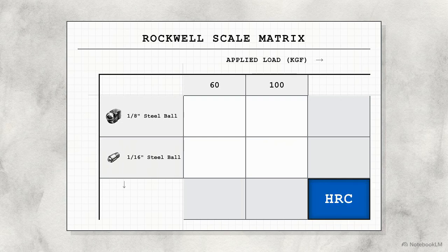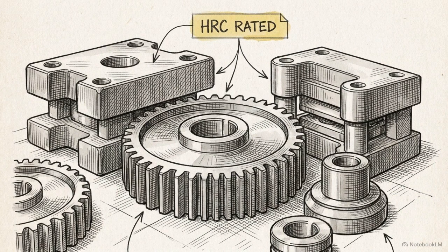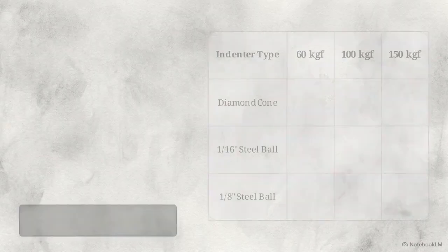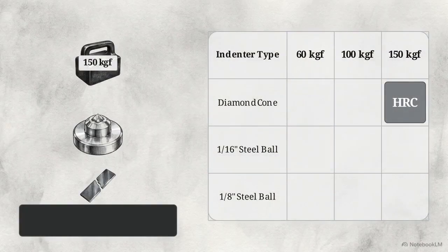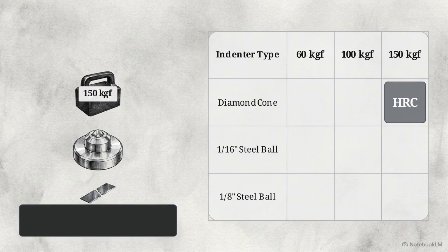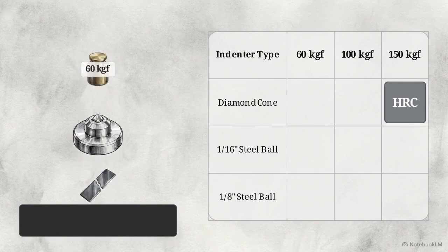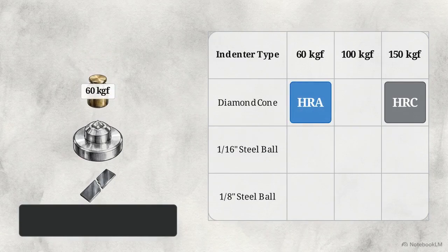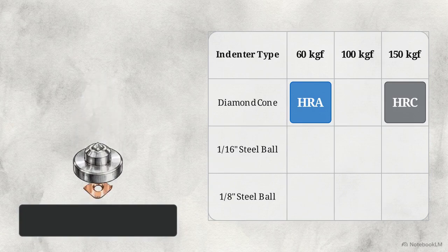The intersection of the diamond cone and the 150-kilogram load creates the standard scale, HRC. HRC is the heavy-duty standard explicitly reserved for hardened steel, heavy gears, and industrial dies. However, testing a thin carbide blade with the extreme HRC load would crack the specimen instantly. Dropping the load to 60 kilograms while keeping the diamond indenter creates scale A, or HRA, calibrated for brittle materials.